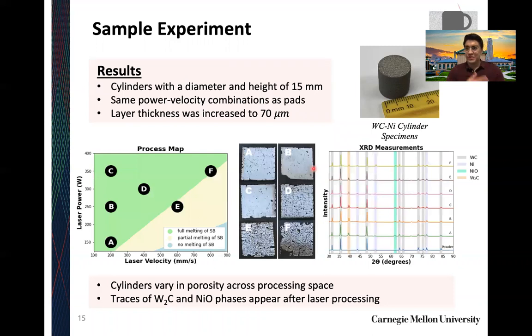So very similar to the previous slides. I'm only showing 5 cross sections for the sake of time, and you can see these 5, excuse me, 6 are spread out all throughout the place, and you can see various degrees of porosity, really. Granted, these are superimposed over the single bead regions, which were 50 microns in layer thickness. So it's almost like you have to actually take this threshold line and increase the slope. So therefore, D might actually end up being in partially melted regions for a 70 micron layer thickness. Hence why we see a lot more porosity in D here, very little porosity in C.